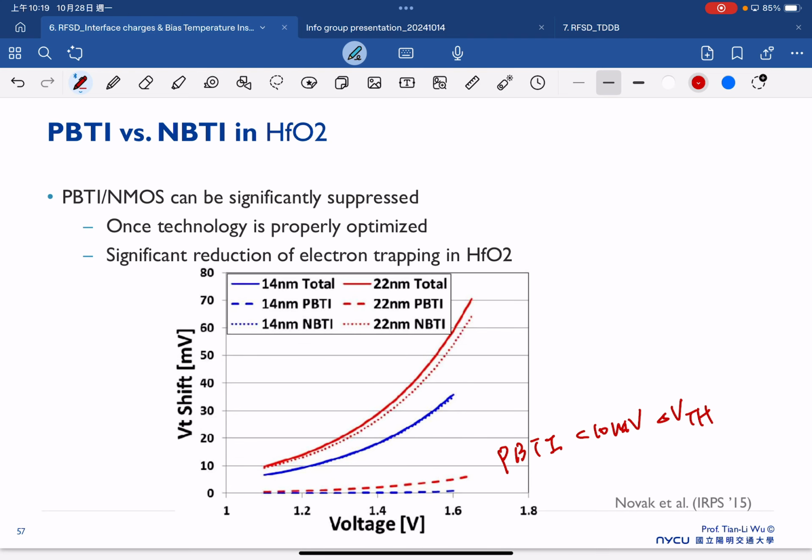So our NBTI still remains an issue. This is our NBTI, because the shift for NBTI is still beyond 30 millivolts. But even if you look at the trend for this one, it dramatically increases. Of course, our operation voltage will not be that high because we will try to reduce our power consumption. So we will try to minimize our operation voltage. But still we can see the NBTI remains a